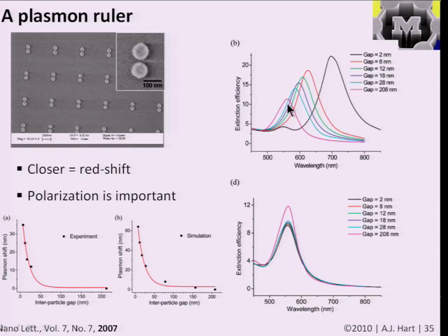And it turns out there's also another study that tries to attack this problem in a bit of a different way, using electron beam lithography, which is able to basically pattern pairs of particles by modifying a polymer and then depositing the film in there. This group was able to create pairs of, you could say, metal discs with different separations.